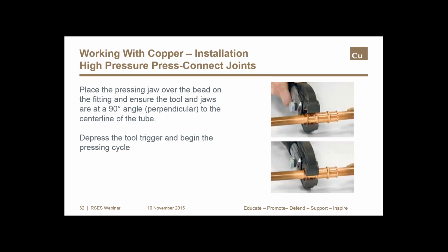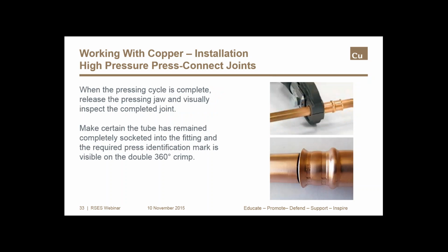The next steps are to properly place the pressing jaws on the fitting and start the pressing cycle. As this slide shows, the pressing jaw should be centered on the tube and placed over the bead on the fitting. A trigger starts the pressing cycle. It's important when the pressing is complete to make sure the tube has remained fully inserted. And again, the insertion mark that we put on the tube at the beginning of the process will tell us that the tube stayed where it belongs.